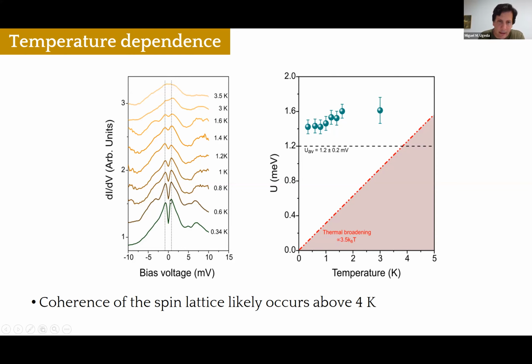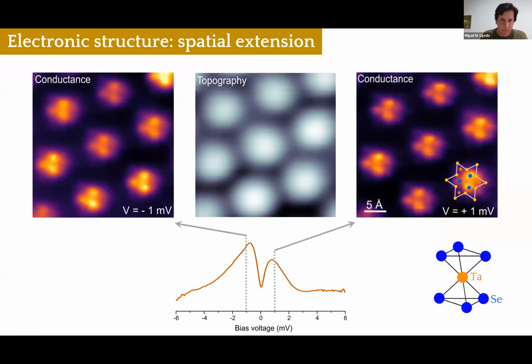But the interesting thing is that the distance between the peaks basically does not vary with the temperature, and we believe that probably the coherence of the spin lattice likely occurs at temperatures larger than 4 Kelvin. The only reason why we don't see it at 4 Kelvin is because of the limited energy resolution at 4 Kelvin, which is about 1 milli-electron volt. Okay, so we have also studied the spatial extension associated to these two peaks.